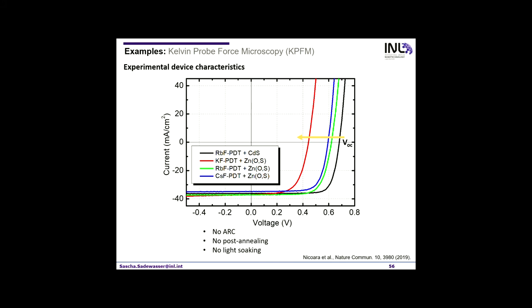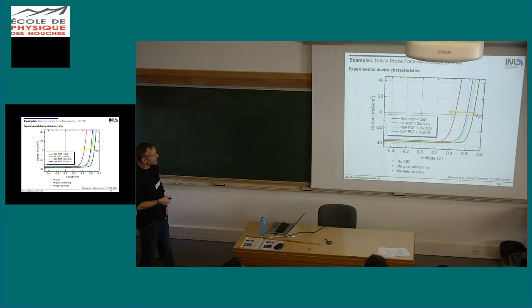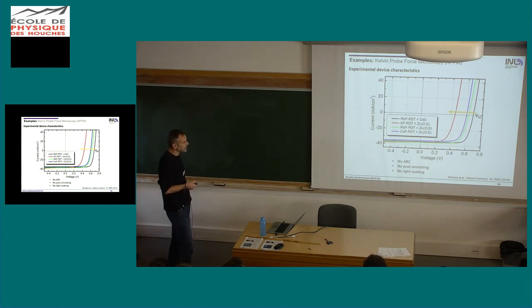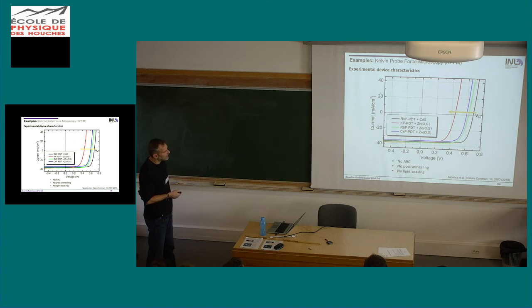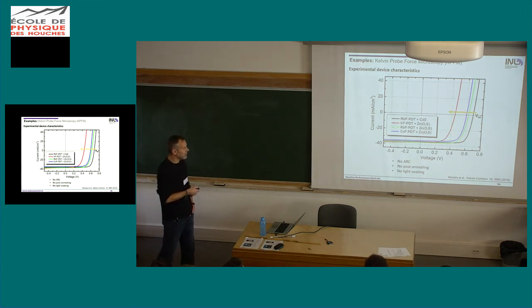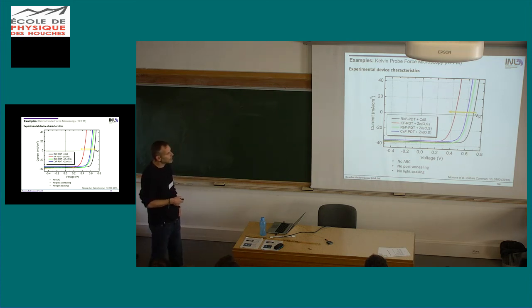So then we can look at IV curves from the samples we looked at. Some parts of these samples were finished into devices, and we looked at the IV characteristics. We can see in the current there's a minor change, but there's a huge change in the voltage. So the potassium one was not working very well, actually. The potassium has the potential to be much better than that, but this very sample was not very good.